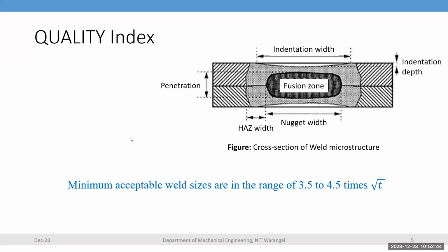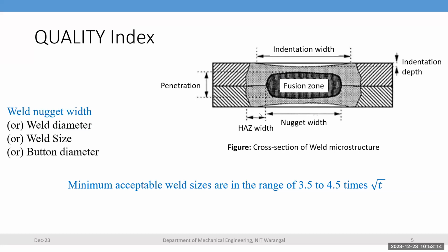Then there is the nugget width and indentation depth, and because heat is involved in the process, the heat is transferred to the other portion of the weld region. Then you can have a heat affected zone. This is a very dangerous zone compared to the fusion zone because it alters the mechanical properties once heat is transferred to the surrounding material. So the weld nugget width is the weld diameter, weld size and button diameter.